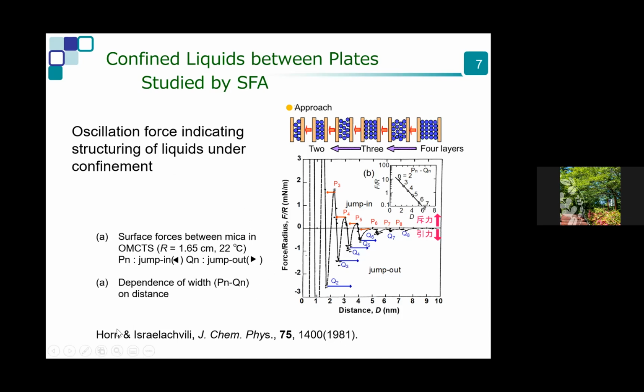Horn and Israelachvili found that when they confined OMCTS, a very spherical molecule, in a narrow gap, there is an oscillation in their forces, which corresponded to a layered structure of molecules. And that was a very new finding at that time.